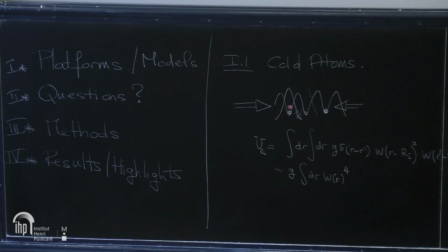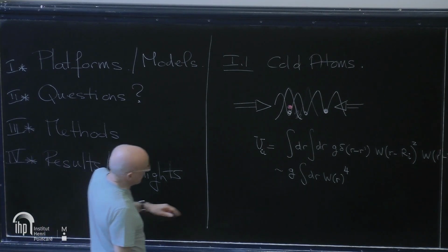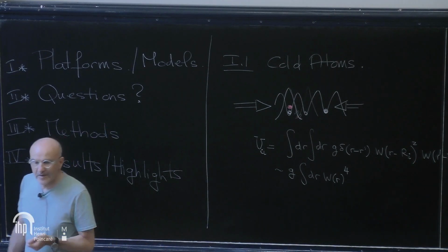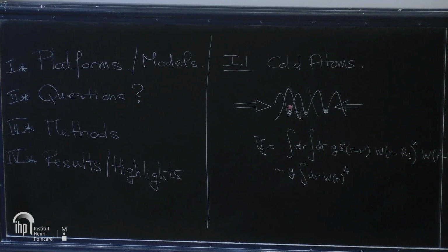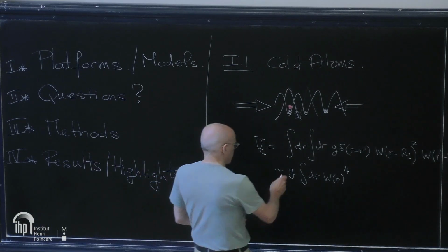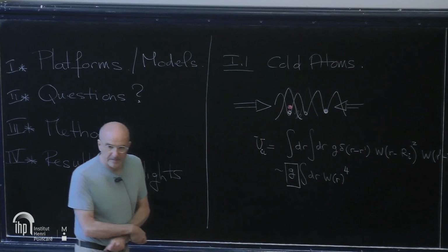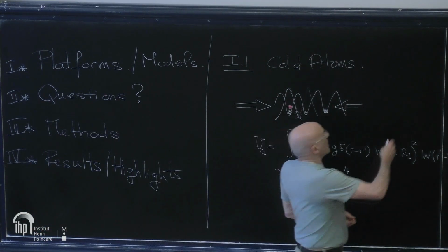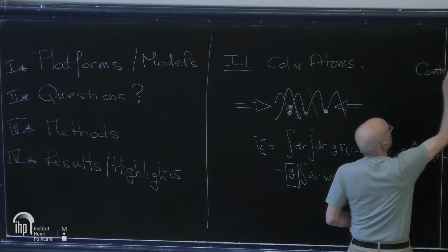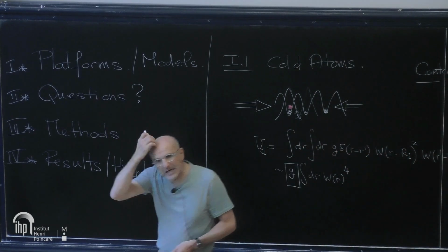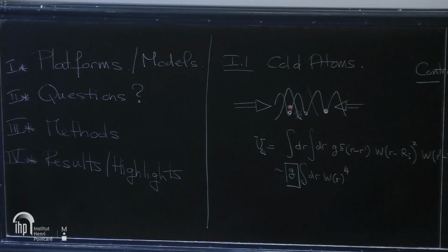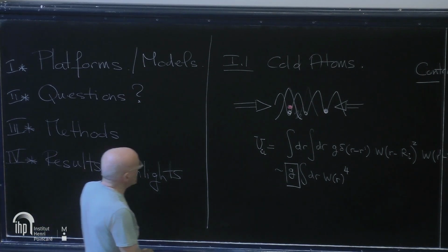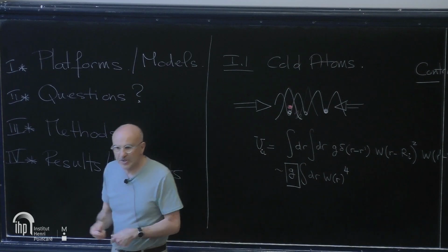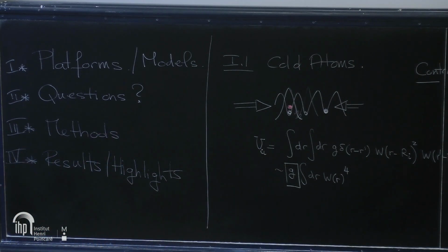And of course, g can be controlled because it is proportional to the scattering length, and to some extent, we can control the scattering length even in the presence of the lattice by the so-called Feshbach resonances. So we have control on g. At least the experimentalists have control on g. And I've pronounced one important word here, which is control. These platforms are highly tunable and controllable, and the tools at the disposal of the experimentalist to control these systems are the strength of the interaction, which can be tuned with Feshbach resonance, which means ultimately magnetic fields,